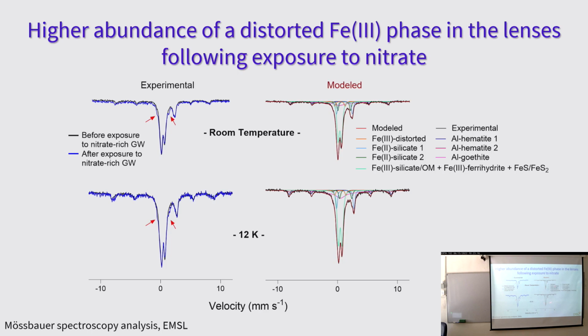On the right, I'm presenting the modelled data before exposure to nitrate. So the right-hand side simply teaches us about the different species of iron that are initially present within our sample. So we see here we have various iron oxyhydroxides, so we have hematite, goethite, ferrihydrite, a combination of iron 2 and iron 3 minerals, and also iron sulfide.